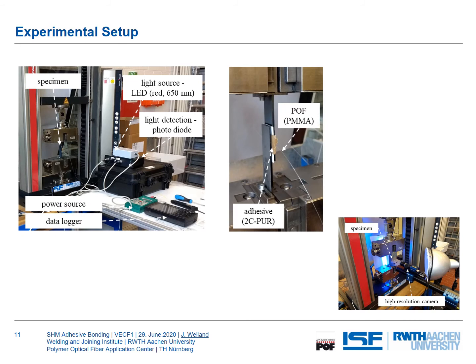On this slide I want to show you our experimental setup. On the left, that's what I told you already. We have the specimen in the testing machine. We have our red LED and the photodiode. We can save the data with a data logger, and we have a power source. In the middle you see our specimen with integrated POF and 2-component polyurethane adhesive. That is one experimental setup. Another setup you can see on the right. There we take a look at the behavior of these bonds with a high resolution camera, and we really want to look at the cross-sectional shape of these bonds. Therefore we cut the adhesive and also the fiber which is coming out on the side from the bond.